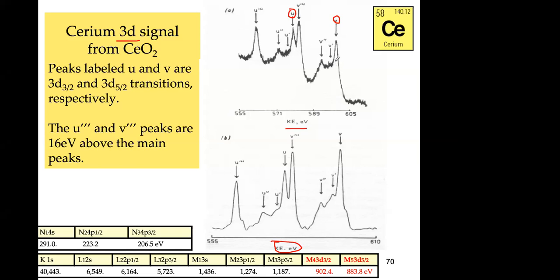So you will have 3d 5/2, and 3d 3/2 will be this one. All these additional peaks here, here, and here, are shake-up transitions. So they are satellite peaks. And this is a very high atomic number element, and you have a lot of levels. So you will have those transitions. This electron may lose energy because of this transition, or this transition.